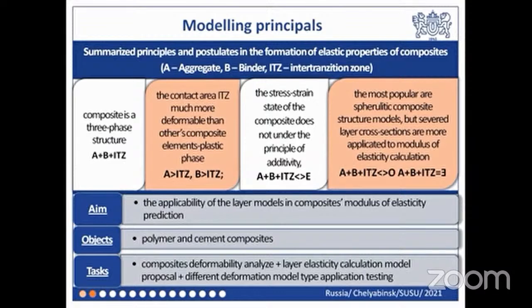Second, the contact area ITZ realizes surface energy, so ITZ deformability is mostly higher than other composite elements. ITZ is the basic element of viscoelasticity. Third, the stress-strain state of the composite does not follow the principle of additivity. And fourth, the most popular are spherulitic composite structure models, but layered cross-sections are more applicable to models of